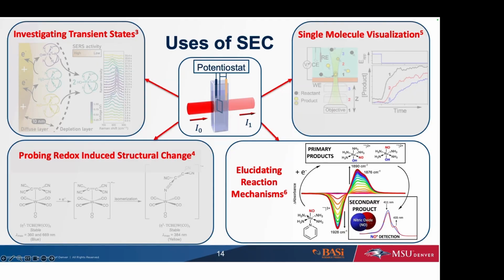And so what they found out is that this mechanism really relies on the cis-trans isomerization, and the trans effect can actually be used in this case to deliver the nitro radical in a more controlled manner, as they started to understand that when these isomers are generated, they're generated via this outer sphere electron transfer reaction that then triggers this chain electron transfer reaction that then releases the nitro radical into solution. And so this is just another example of how FTIR SEC can be used to elucidate reaction mechanism.